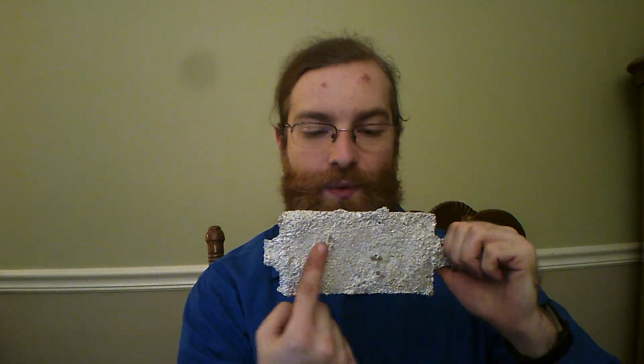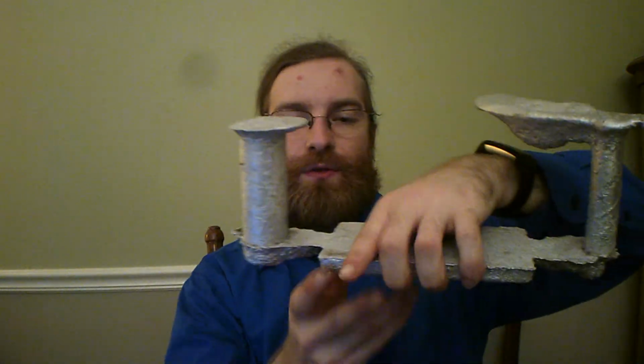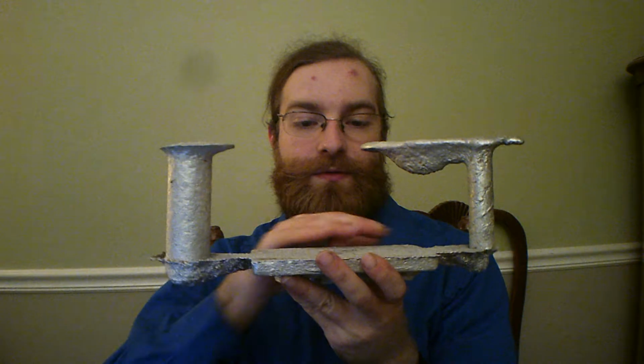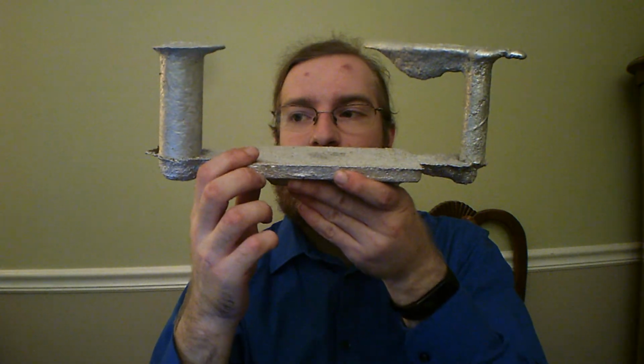Now, since I did not have a completely level surface in the sand, when I put the pattern down on it, that is all of the irregularities that were in the surface that I put the pattern on. Time number 2, I did it the right way and actually put this on a molding board, rammed the drag up over it, which is the bottom half, then rolled it over and rammed the cope up over the flat section. Came out with many fewer inclusions and also a much flatter underside.